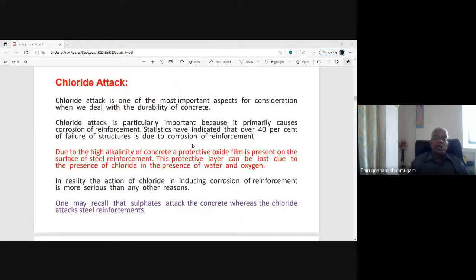Chloride attack. Chloride attack is one of the most important aspects for consideration when we deal with the durability of concrete. Chloride attack is particularly important because it primarily causes corrosion of reinforcement. Statistics have indicated that over 40% of failure of structures is due to corrosion of reinforcement.